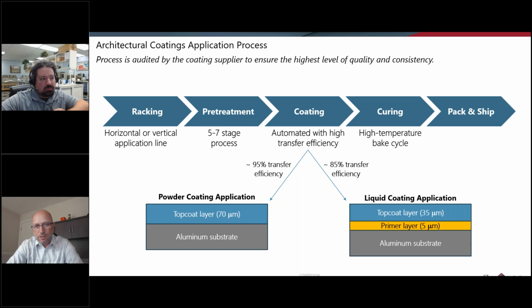If you're using a liquid coating, which is the one on the right, your transfer efficiency is actually pretty high. It's about 85%. And when I'm talking about transfer efficiency, what I'm referring to is if you had a can of spray paint and you're spraying a piece in your garage or in your yard, a lot of that overspray is going to go past the part and cannot be regathered or reused.